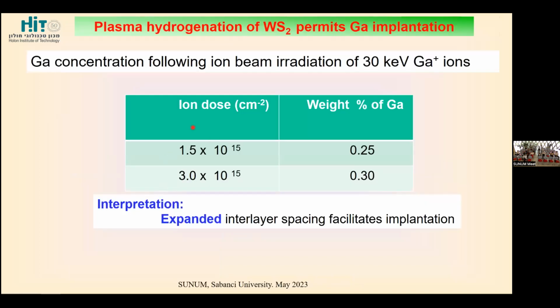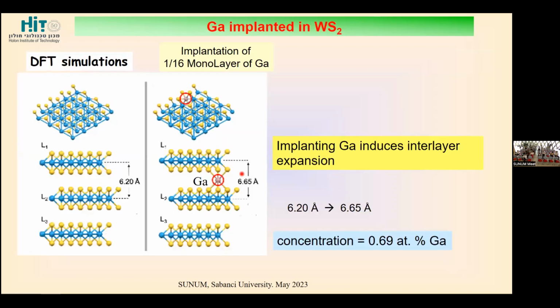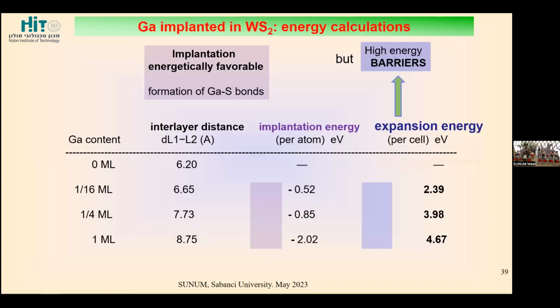Here you can see some improved experiments with weight percent of gallium. The interpretation for this successful implantation was expanded interlayer spacing because of the previous hydrogenation of the materials. Here you can see some simulations. Gallium implantation requires an increase in the interlayer space from 6.2 to 6.65 angstroms. Quite a lot of energy, but we already did most of this by hydrogenation. In this case, we can achieve up to 0.7 atomic percent of gallium, even more than we got through the experiment, so there is some room to improve the experimental procedure.